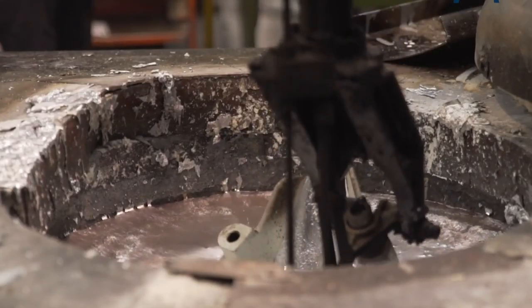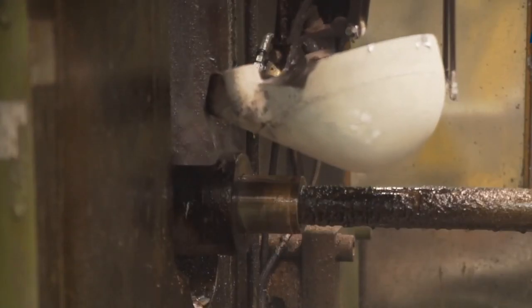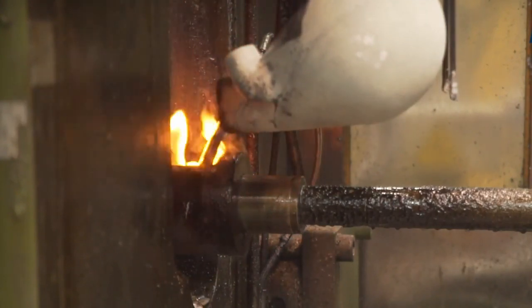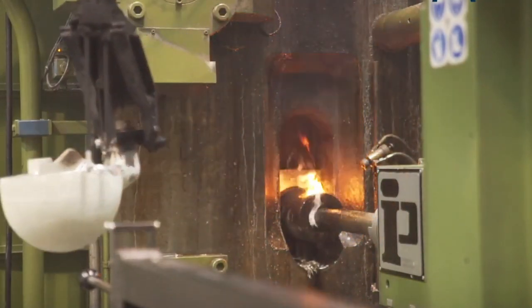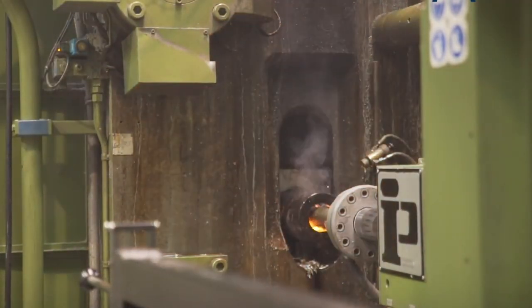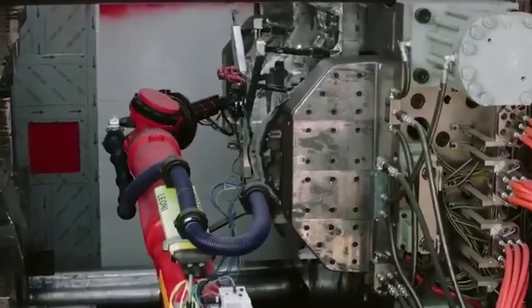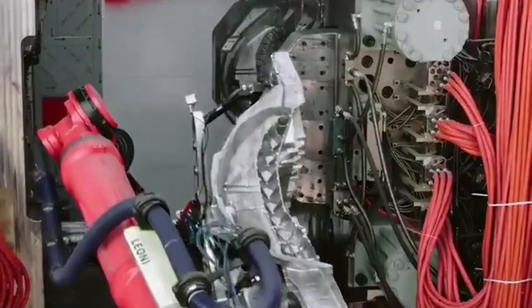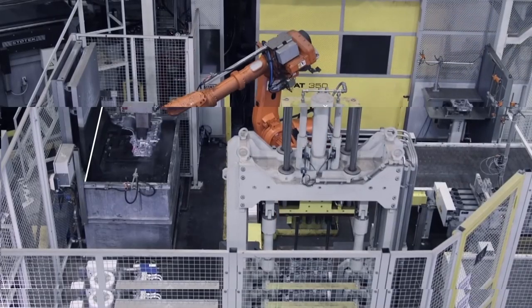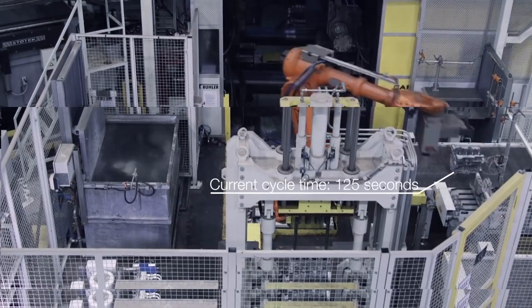A portion of the molten aluminium is transported from the holding oven to the shot chamber of the Gigapress at a temperature of 750 degrees Celsius, and then, using a high-speed plunger, it is forced into the mould with 8 milliliters of lubricants. The mould is then opened and the raw casting is removed at a temperature of 400 degrees Celsius. A robot reaches in, removes the casting, and places it in a quenching tank to reduce the temperature from 400 degrees Celsius to 75 degrees Celsius.